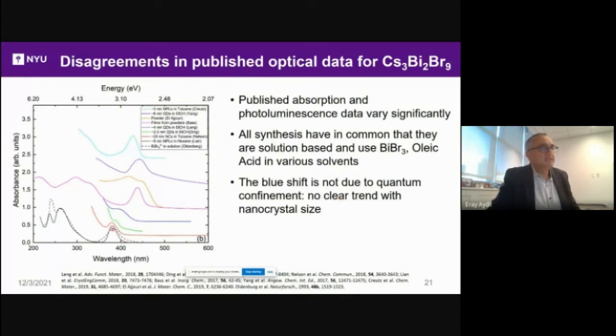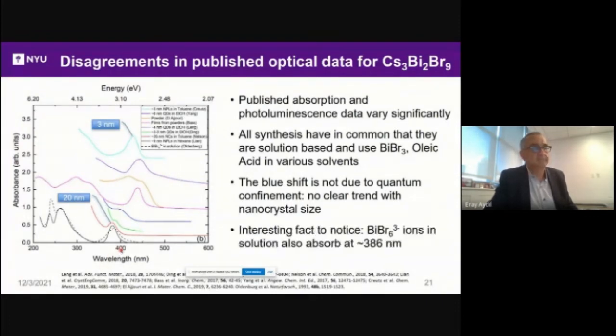Now, you might say, well, they're making nanocrystals, so this shift might be due to nanocrystal size quantum confinement. And it's not, because there is no clear quantum confinement trend. You would expect smaller nanocrystals to appear blue shifted compared to large nanocrystals. And here I show 2 examples and the trend is reversed. So it's not due to that, okay?